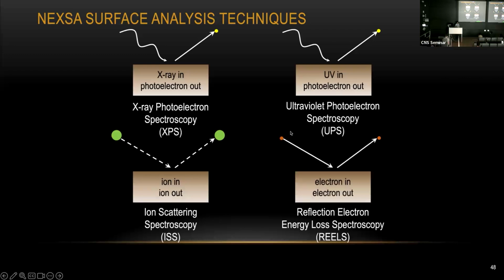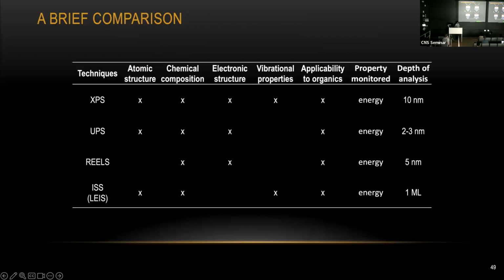For REELS, it's pretty much the same idea as ion scattering, but the difference is that we are not using ions, we are using low energy electrons. The same electron hits your surface and scatters back to the detector. Different measurements can give you different information. It really depends on what you're looking for. And here is simply a table to illustrate what each measurement can do. Earlier you already learned pretty much what we can do with XPS. For UPS, you can see the sampling depth is much shallower, only 2 to 3 nanometers.